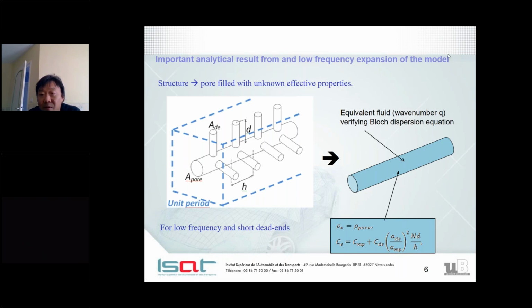So, wave number... we have a wave number, and in the model we found that at very low frequency, and in the situation where we have short dead ends compared to the wavelength, so the dead ends are not too long, then we have a very simple low frequency expansion of the result of the theoretical dispersion curve, which shows that the effective density of the fluid in the equivalent fluid is that of the main pore without dead end.